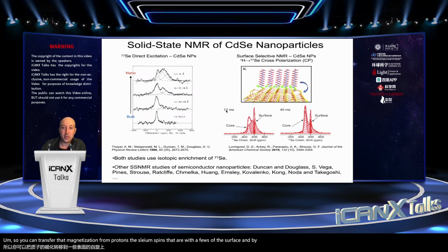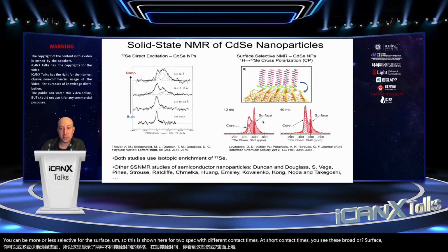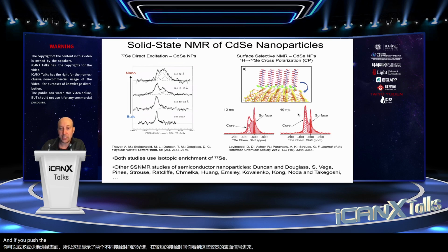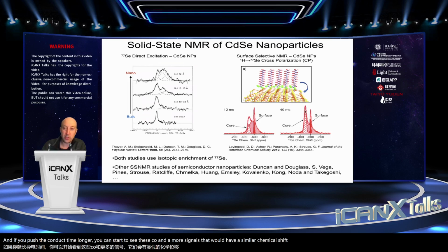And by tuning the contact time in the cross-polarization experiment, you can be more or less selective for the surface. This is shown here for two spectra with different contact times. At shorter contact times, you see these broader surface signals coming in. And if you push the contact time longer, you can start to see these core NMR signals that would have a similar chemical shift to bulk cadmium selenide coming in.